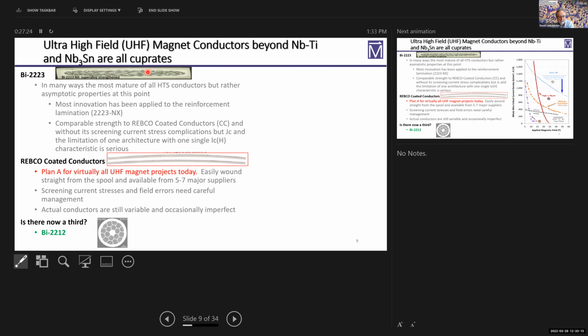And so actually what happens is that people said, you've got to go towards texture. And the first material which was generated this way was bismuth 2223, which looks really good because TC is 110 Kelvin. And there is a bismuth oxide double layer in these materials, which is micaceous. So in fact, if you put a powder of bismuth 2223, actually it's bismuth 2212 plus some stuff, into silver tube, you can mechanically fabricate that very well.